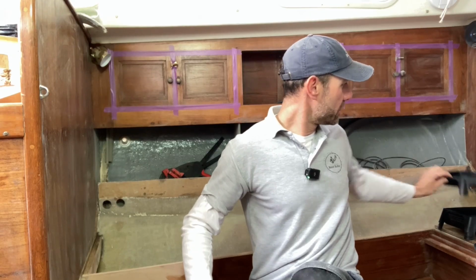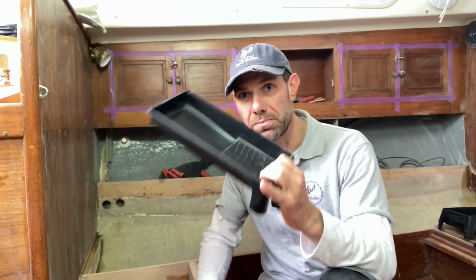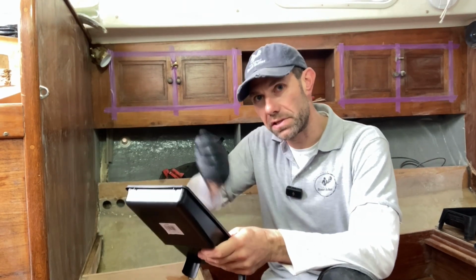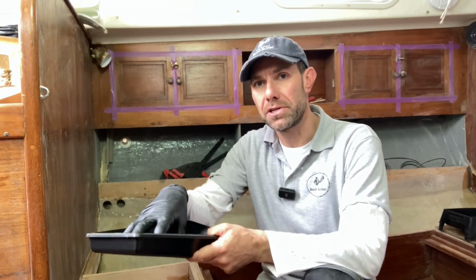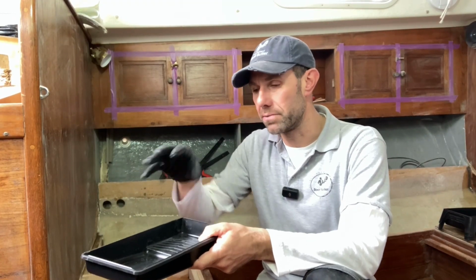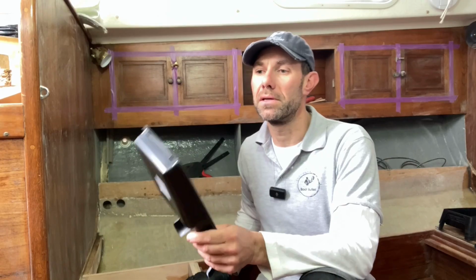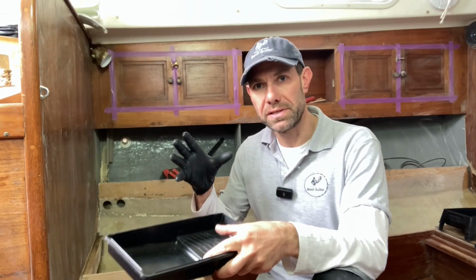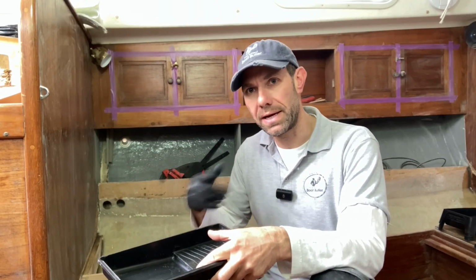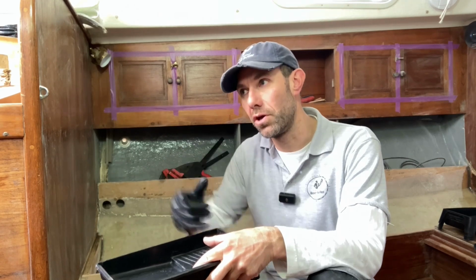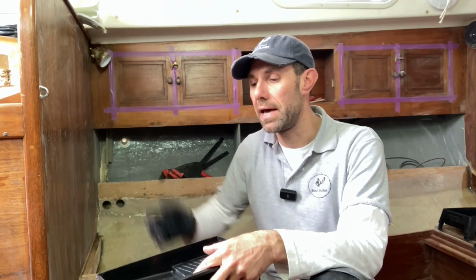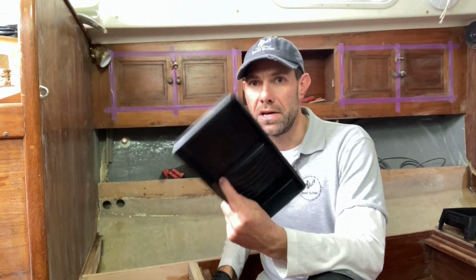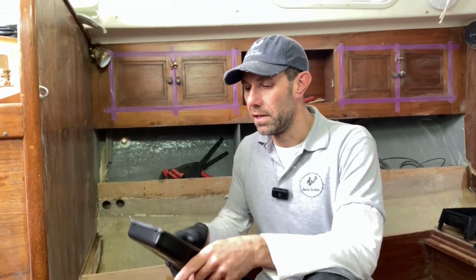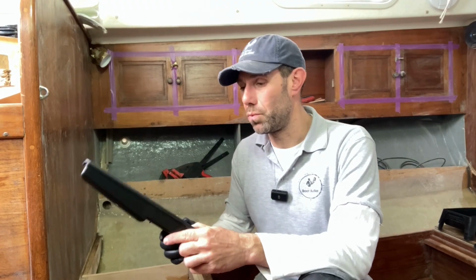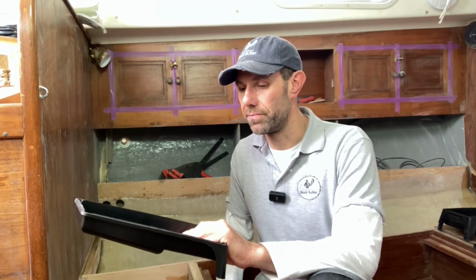Once I have catalysed the resin, I'll be putting it into a small tray like this, because it's just easier to roll it out, but also this has a much larger surface area than keeping a bulk amount of resin in a pot, because in a pot there's always a risk that it will start heating up, and the more it heats up, the faster it will cure, which means it will create more heat. It starts exotherming in the pot, and you can have resin boil over and start bubbling and basically cure way too fast, which is the best case. The worst case is it can start smoking and cause a real problem.